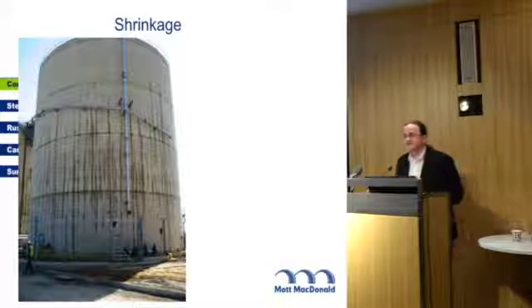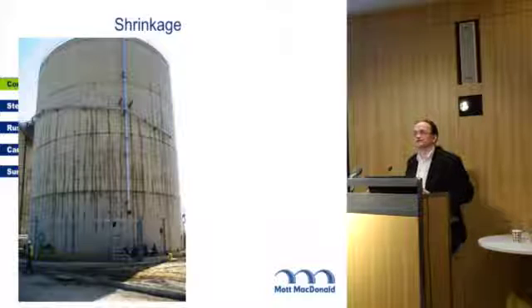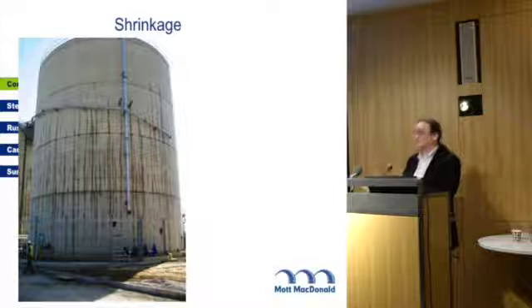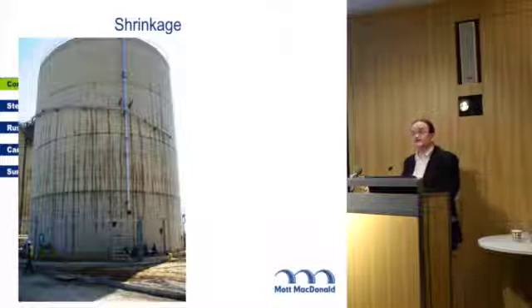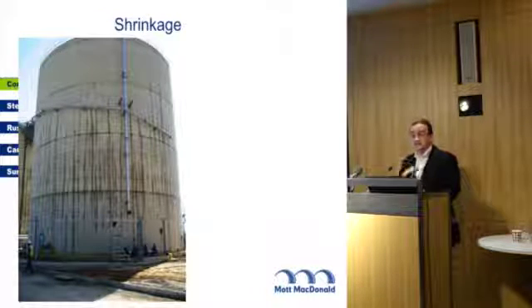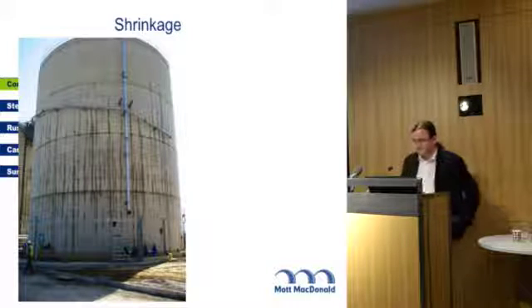In this case, concrete occasionally does a very useful thing called autogenous healing. The cracks self-heal with a bit of time. We measured them all, they were all in requirements with the design code. The autogenous healing basically filled them up, and after a couple of months with water sat in it, it stopped leaking.